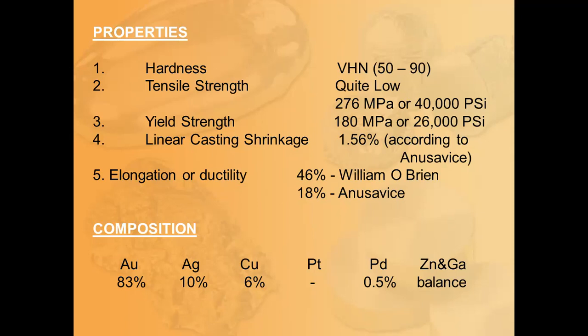And now coming to its composition. It contains gold 83%, silver 10%, copper 6%, palladium 0.5%, and zinc and gallium in trace amounts.